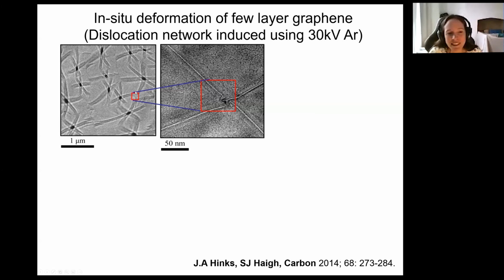Okay, so we see these beautiful hexagonal defect structures when we perform the same experiment on a few layer graphene rather than monolayer graphene. And when you zoom in, you can see what's happening at the interface between these zones, and these zones are demonstrated by the fact that you have this hexagonal pattern, which is the zone axis. So very similar to Kikuchi patterns, which many electron microscopists are familiar with. This is the center of the zone axis, and around this is where the material is off zone. So it's effectively forming a dome, with the domes joined together by these dislocation lines.